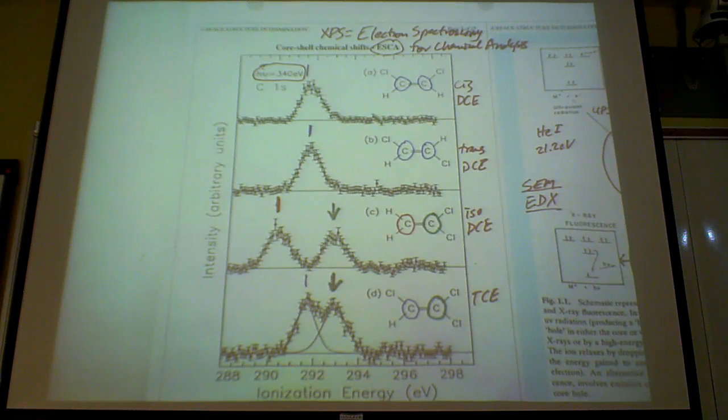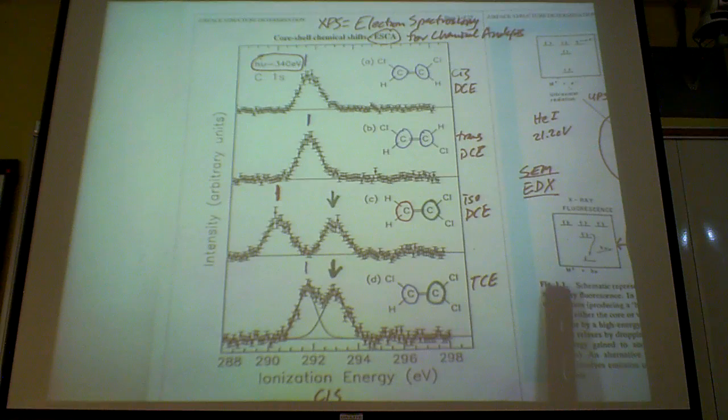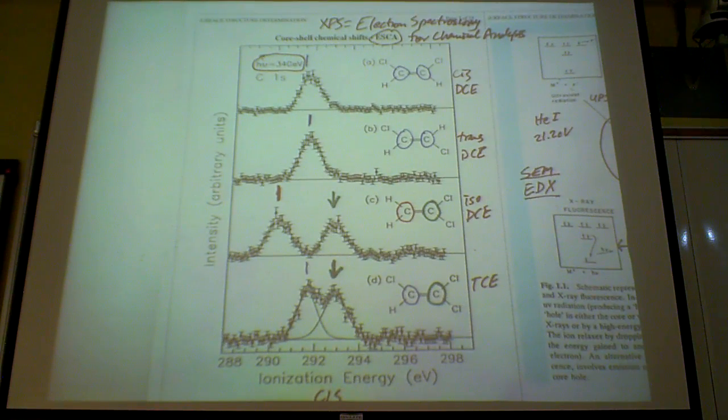And chemical shift is powerful, as we'll explain later when we talk about electronic structure in nanoscience, because it tells you about the local electronic environment. If you're talking about a silicon wafer, silicon surrounded by silicon will have a different binding energy. Let's say the silicon 2p electron will have a different binding energy compared to the silicon 2p binding energy if the silicon is sitting next to oxygen, as in silicon oxide.